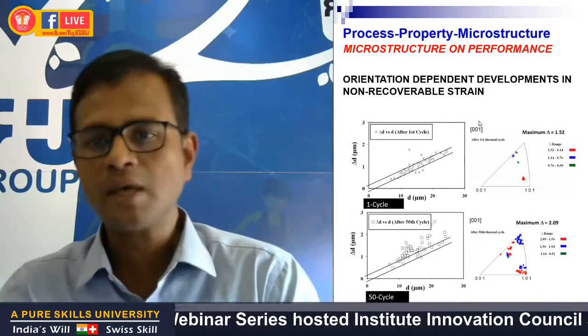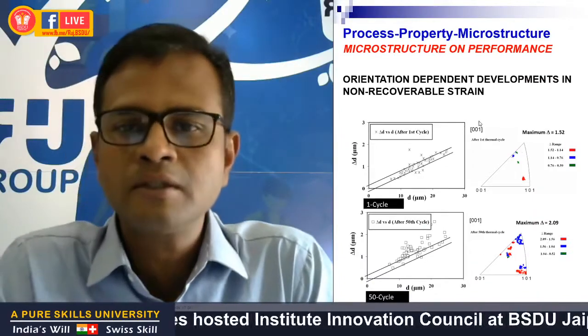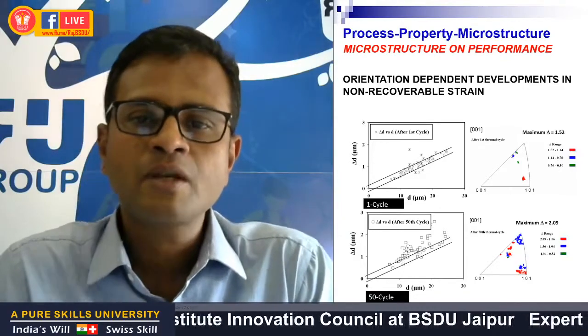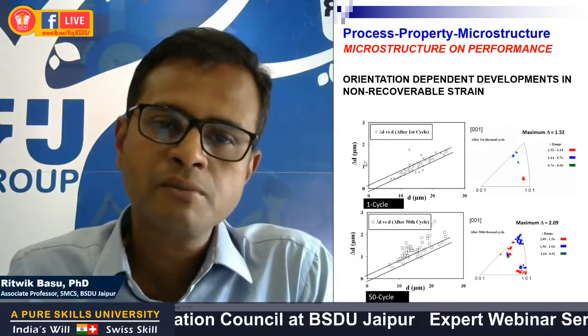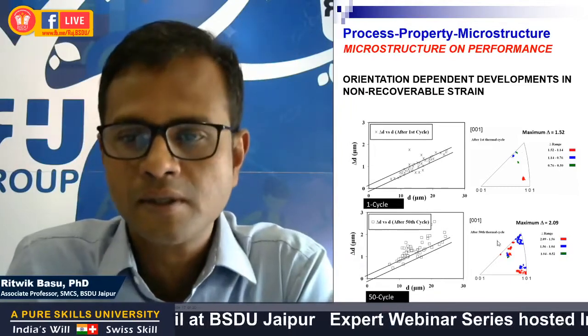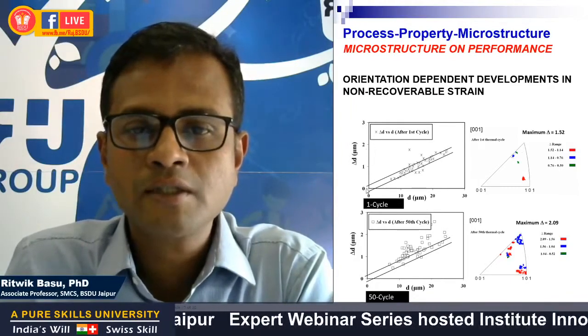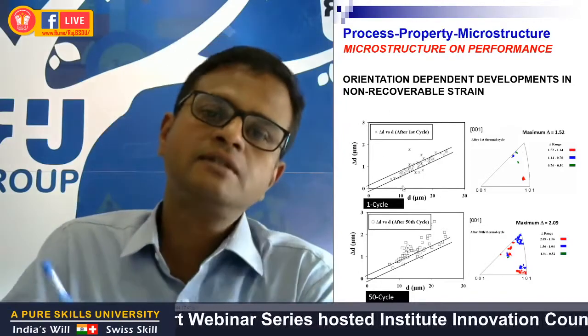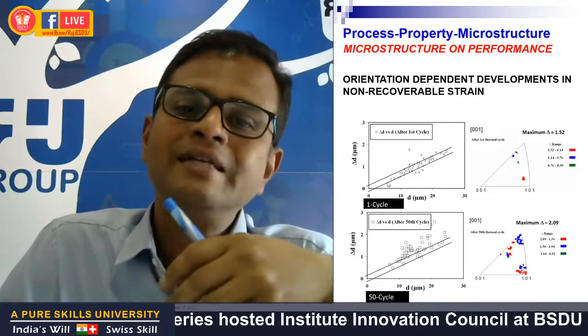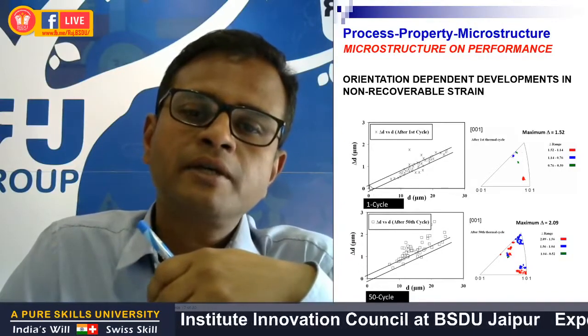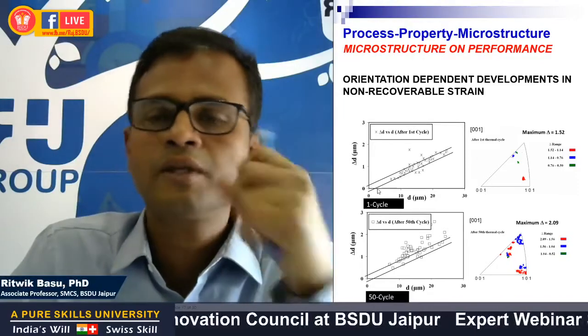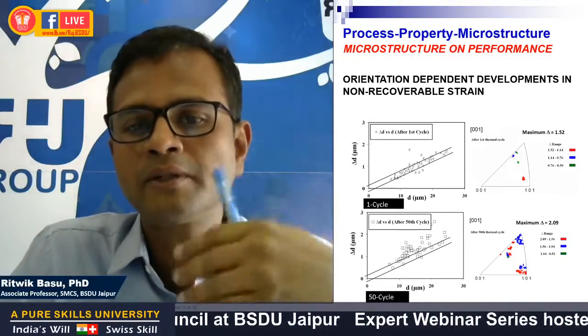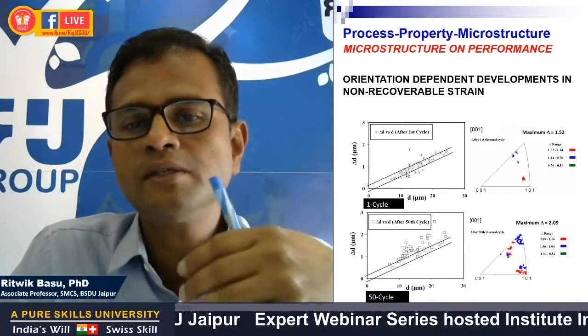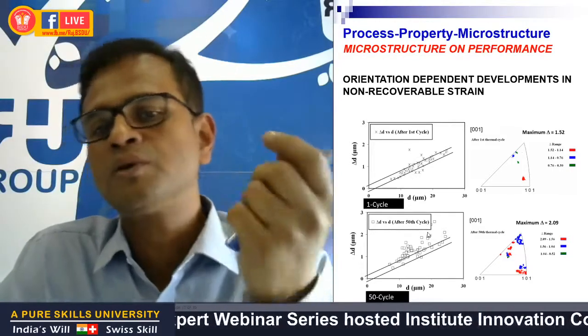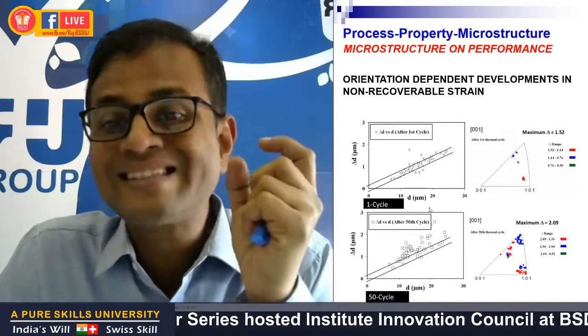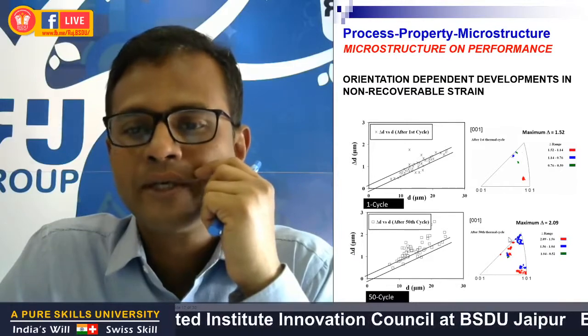So we chose sample D and subjected it to a few more thermal cycles. We went up to 50 thermal cycles. This quantity delta D, or the irreversible strain, as I was stating earlier, is orientation sensitive. And this is brought out in this plot of delta D versus D. After the first thermal cycle, we saw these data points were nearly linear. We then fixed an upper and a lower control limit with our best estimate in between, so that all these data points lie between the upper and the lower control limit. And we found that with an increased number of thermal cycles, these data points moved upward, and the grains that exhibited the highest delta D were sensitive to these orientations.